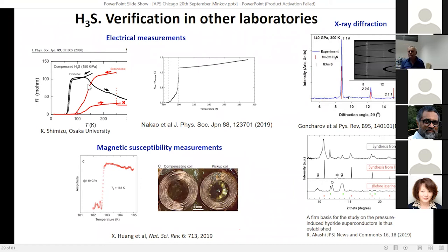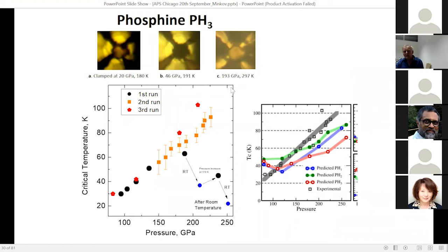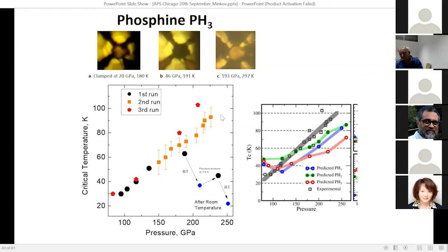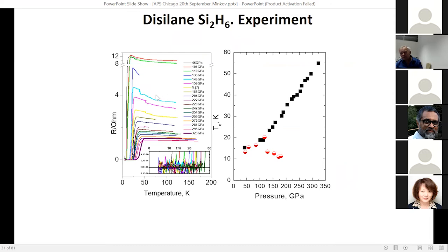This was a lot of work in our laboratory. I won't mention here the extensive theoretical work on H3S, which is very good in correspondence with experiment. We also found superconductivity in hydrogen phosphide. Interestingly, predictions did not find superconductivity in PH3 — which was right — because the active compound is PH2. When we annealed, superconductivity dropped dramatically, providing a very independent test of our experiment.